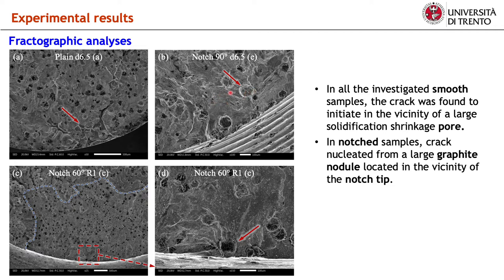However, the smearing action exerted by the fully reversed stress cycle on the fracture surface eliminated characteristic features, striations, pitch marks, permitting to unambiguously identify the graphite nodule as the microstructural constituent originating the fatigue damage. To overcome this difficulty, some notch samples survived after 5 million cycles were retested by applying tension-tension stress cycles until final failure. An example of this obtained fracture surface is shown here at two magnification levels. The dashed line indicates the front of the non-propagating crack nucleated in the run-out test. Its morphology is much less deteriorated, so that striations are particularly visible here. They clearly point out that the crack nucleated from this graphite nodule.